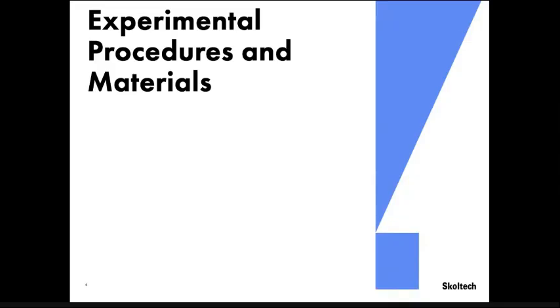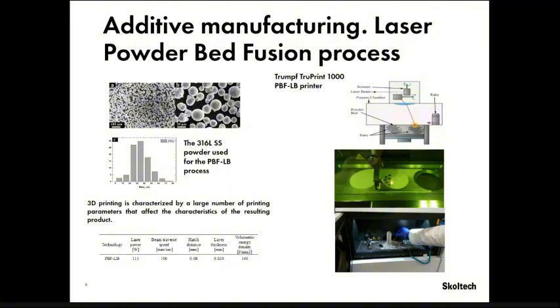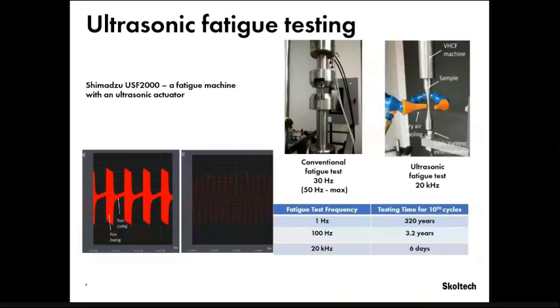It brings us to the main part of the presentation. We used powder bed fusion laser beam technology and printed with stainless steel powder. The parameters are shown on the screen, and we also used machines for fatigue testing. Actually, we did tests for conventional fatigue, but I will not show them in this presentation. Here we will talk about ultrasonic fatigue testing for very high cycle fatigue. It's worth mentioning that it works at 20 kilohertz frequency, and it allows us to test 10 to the 10th power cycles in 6 days, while a conventional fatigue machine, even with a high frequency of 100 hertz, needs 3 years.